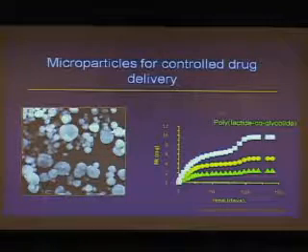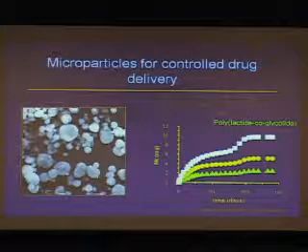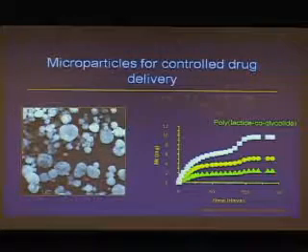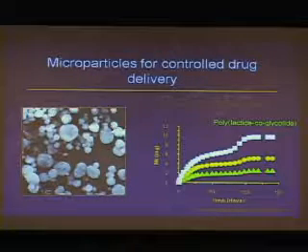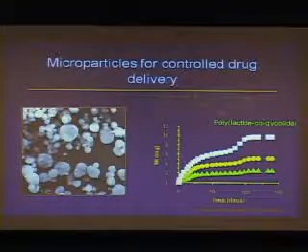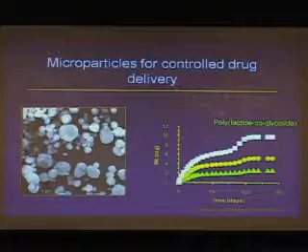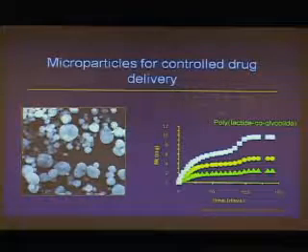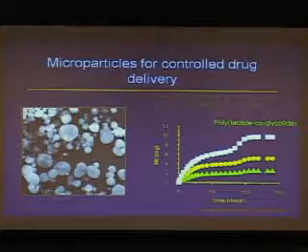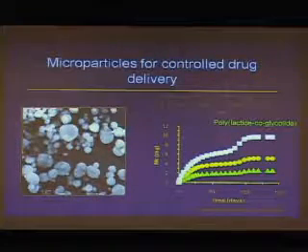And so the first step of that was to make these materials smaller, and this shows about 1990, the early 90s. We were making microparticles about a micron or so in size, so about the size of a bacterium, loaded with drugs. This is made of that lactide glycolide copolymer I mentioned before, a material that's well known to be safe in clinical practice. And these are loaded with drugs, and you can achieve some of the same kinds of things I described with those wafers.